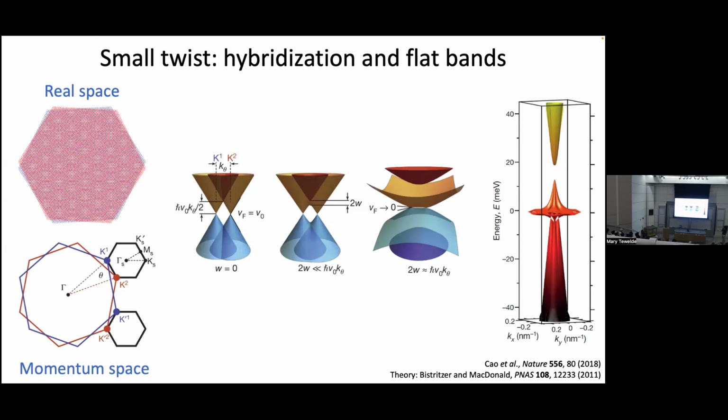And the idea is this is a realization. It's called magic angle twisted bilayer graphene. At this particular angle, you have a situation where the kinetic energy is very, very small. And therefore, Coulomb repulsion between electrons dominates. And in some ways, this mimics aspects of strongly correlated materials.